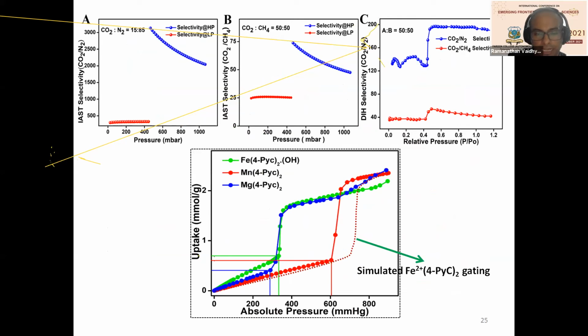Based on the hard-soft gate control, the gating pressure for this iron MOF should have been somewhere here. The dotted line shows where the gating pressure should have been if it had been Fe2+. But in the experiment, I am seeing that the gating pressure is at a much lower pressure, which means it is opening very easily. It does not need that much force of CO2 to open it. This is completely against what you would expect, because Mn2+ is a harder acid compared to Fe2+. But you are seeing that it falls below in terms of pressure, which means you have more hardness at the iron side. This completely made us wonder what is going on.